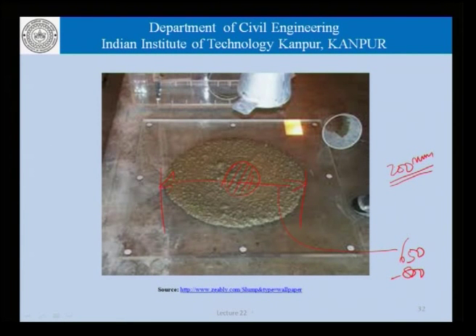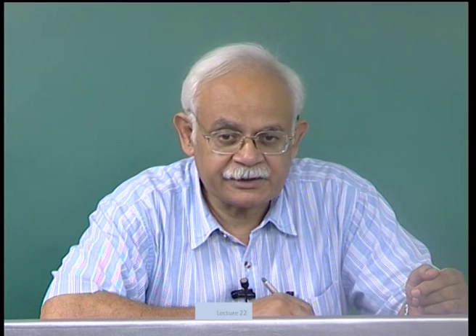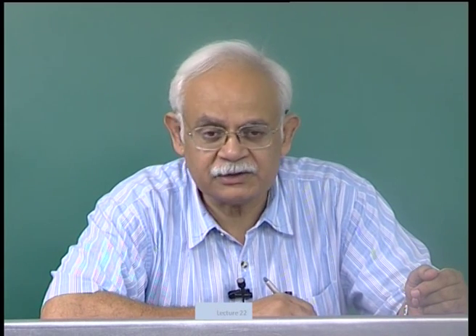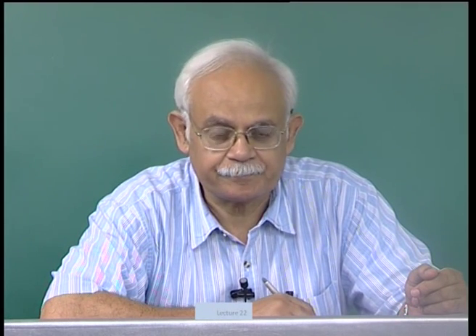When we are evaluating the concrete using the slump flow, we should also watch for aggregates having reached the edges. So, it should not happen that the concentration of aggregates in the periphery of the slump flow spread is different from the aggregate concentration in the center. And that is what is likely to happen if the concrete is segregation prone. If the concrete is segregation prone, the aggregate would not move with the mortar towards the periphery.